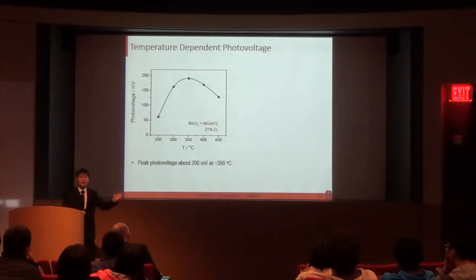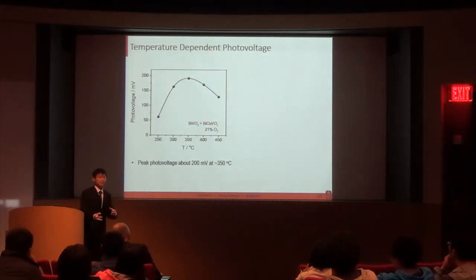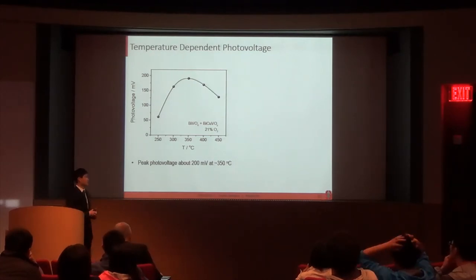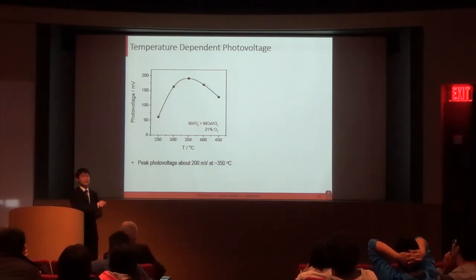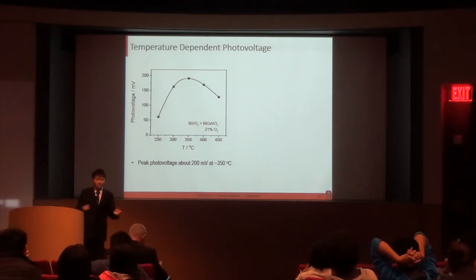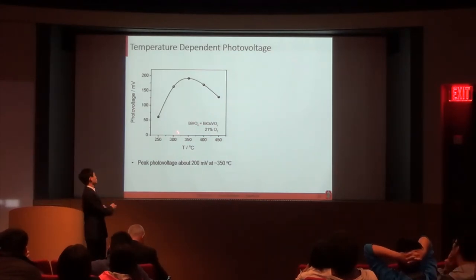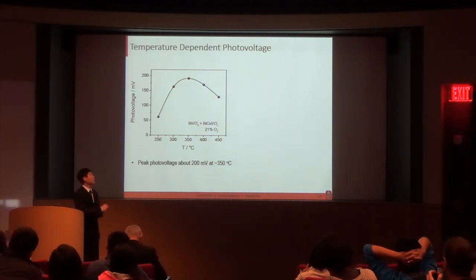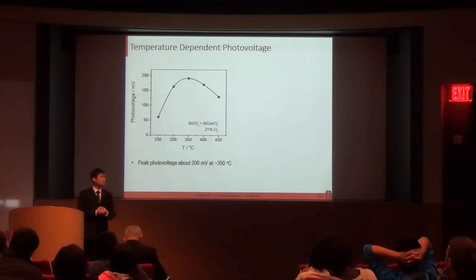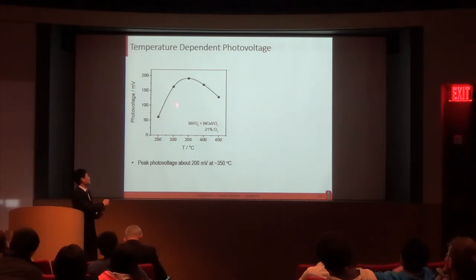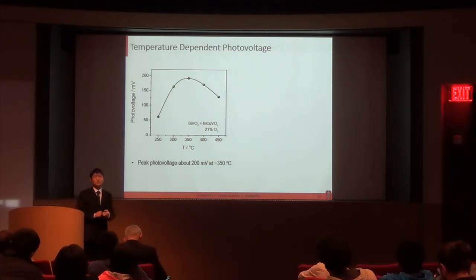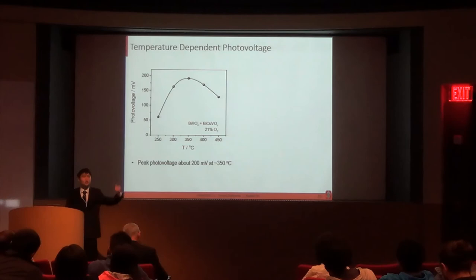And here I show you how the photovoltage behaves as a function of temperature. The first message we can get from this plot is that this device is working. So we do have a photovoltage under illumination. And second, the photovoltage behavior is quite unusual. As you can see, the photovoltage peaks at around 350 degrees Celsius at about 200 millivolts. It is in contrast with solar cells, where photovoltage decreases monotonically with temperature.